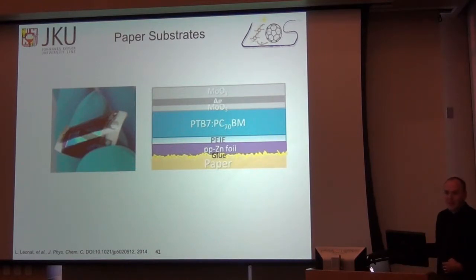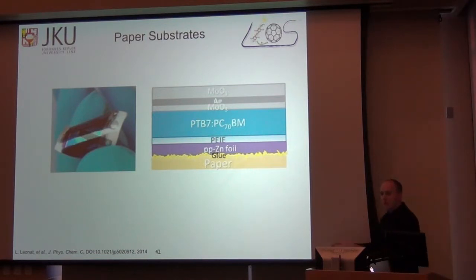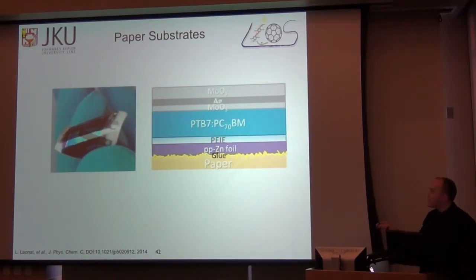And it's also not transparent, so we have to put the transparent contact on the very top. And so here, what we've done is we've glued on a foil, a zinc-coated foil. And this is the same process as if you are making a beer bottle label with shiny foil on top. This is cold foil lamination. It's a very well-known printing process that puts down these metal electrodes. The zinc has a little bit of native zinc oxide on it, but we can't heat it up to 300 degrees. So instead, we just coat that zinc oxide with polyethylenimine as reported above. So here we have zinc as the conductor, a little bit of zinc oxide, but not very well controlled, and then coated with PEIE to make a nice reproducible electron selective contact.